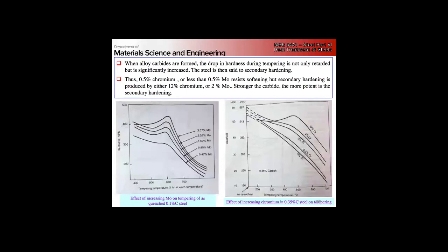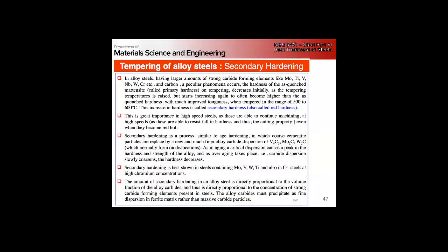What's that? Age hardening, right? So our duplex heat treatment, right? We're growing a fine dispersion of secondary phase particles, giving us an increase in hardness. Then this is overaging, this decrease here. We're coarsening our particles, and they're growing, right? So again, really, really important.